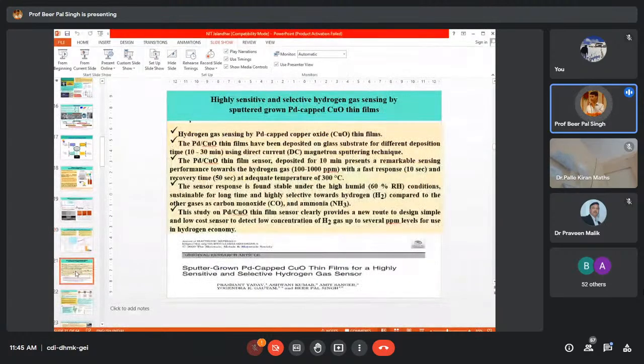This is all about the highlights which we achieved. In that case, we successfully deposited copper oxide thin films by sputtering, and then we capped that with Pd. Pd material will just act as a catalytic agent in that case. And again, we sensed hydrogen at concentrations ranging from 100 to 1000 ppm, and we achieved a fast response of 10 seconds and a recovery time of 50 seconds, at a temperature of 300 degrees centigrade.